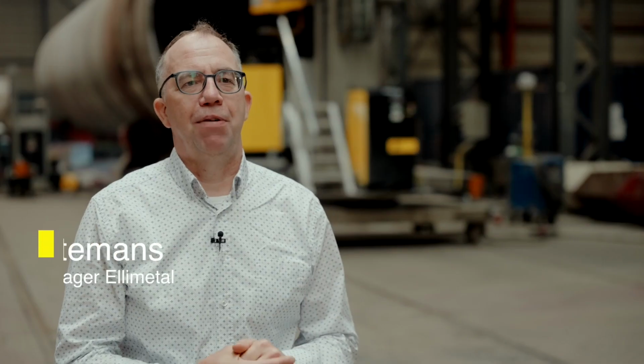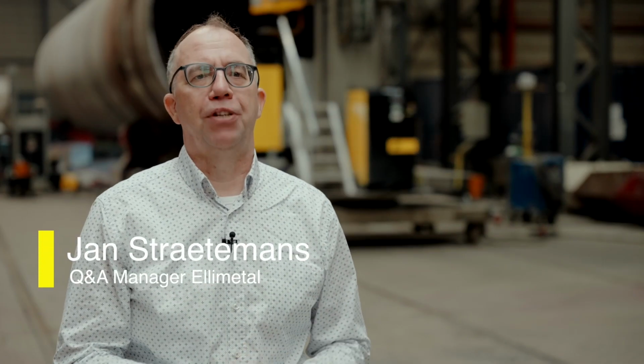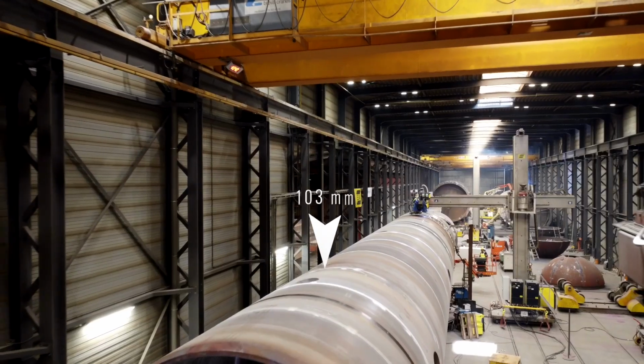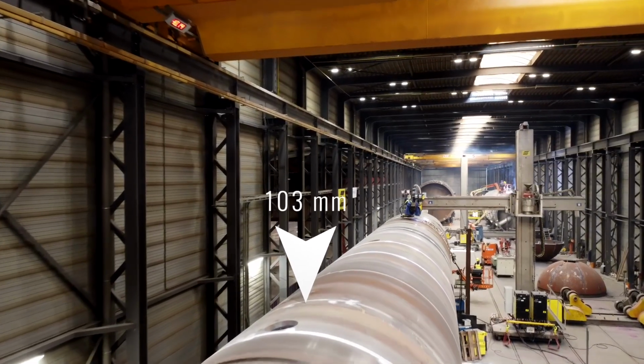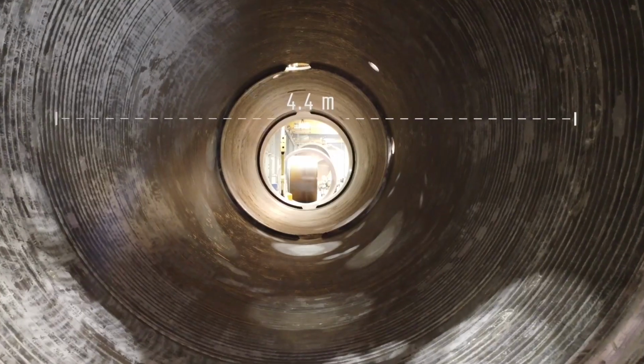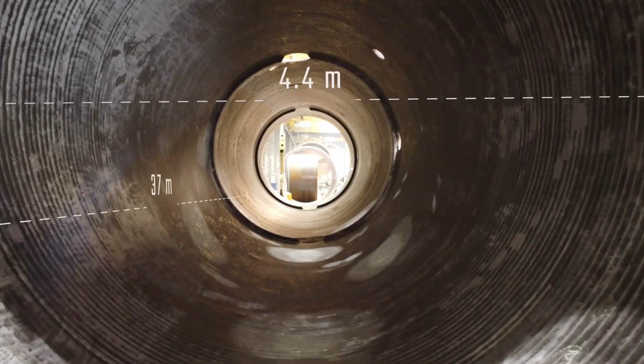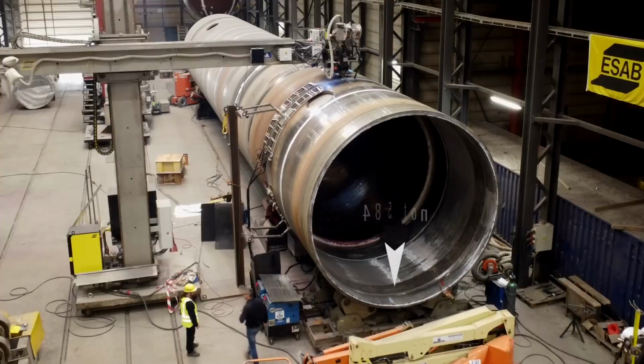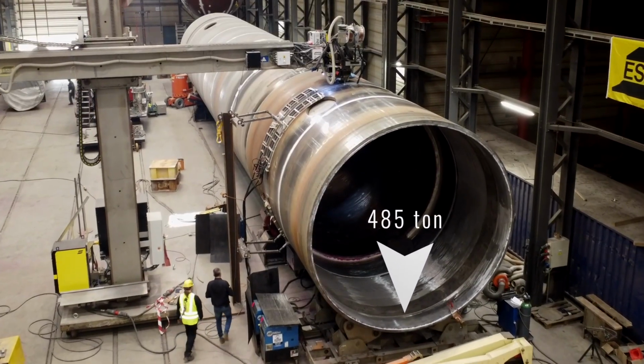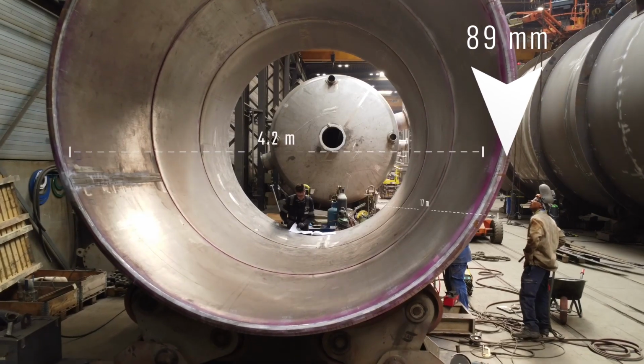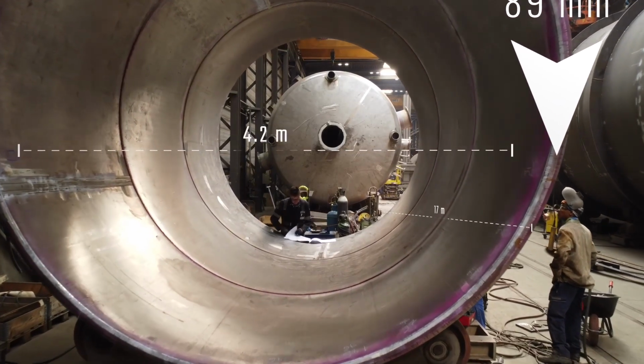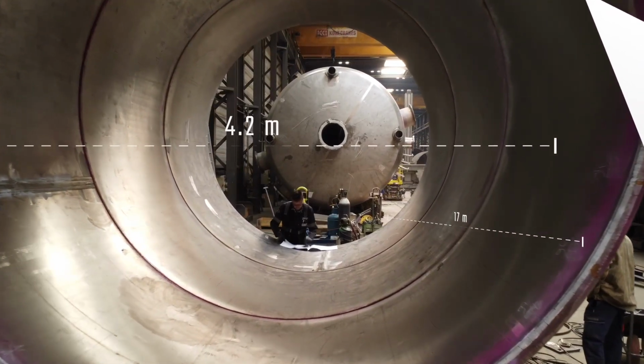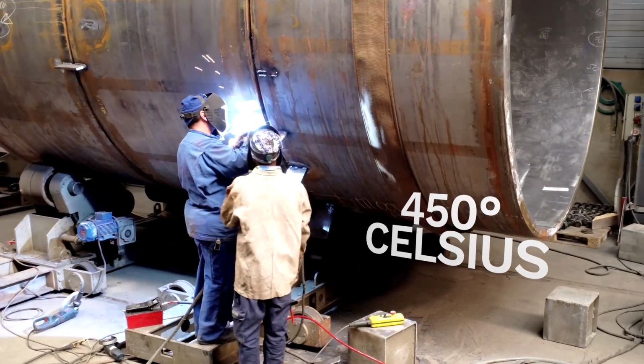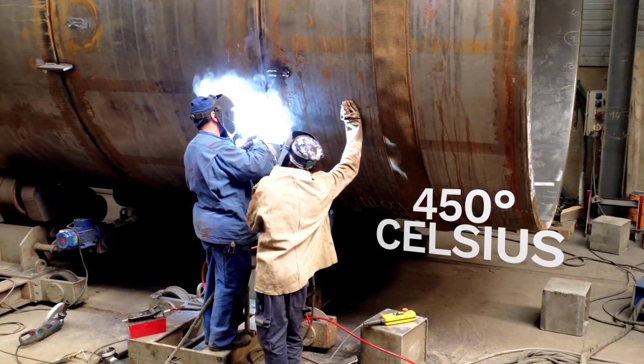This project is a very nice and important order that contains two reactors of 2¼ chrome and 1 moly steel. The larger reactor has a wall thickness of 103 mm and a diameter of 4.4 meter with a length of 37 meter. The total weight is roughly 485 ton. The second reactor has a wall thickness of 89 mm and a diameter of 4.2 meter with a length of 17 meter. The reactor will operate at 450 degrees Celsius.